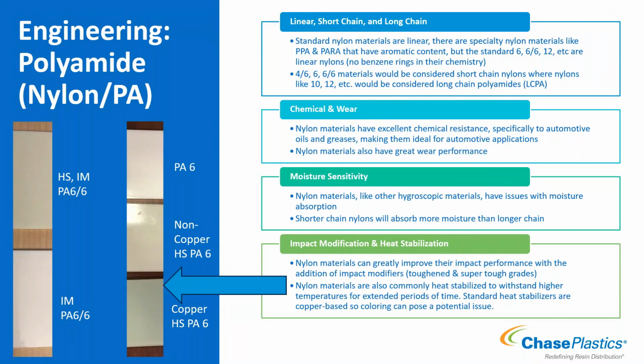Another common thing we'll do with nylon is add heat stabilizers. So for under-the-hood applications where it's going to see elevated temperature for a long period of time, or at least we want to test it for a long period as a safety factor, we can heat stabilize these grades so they can withstand those temperatures for an extended period of time.